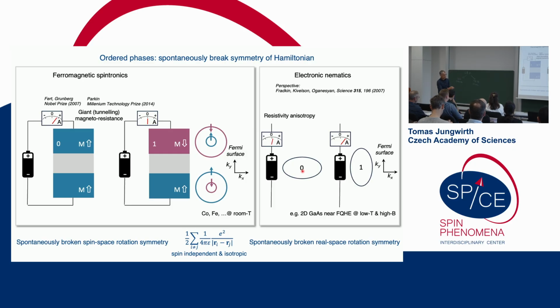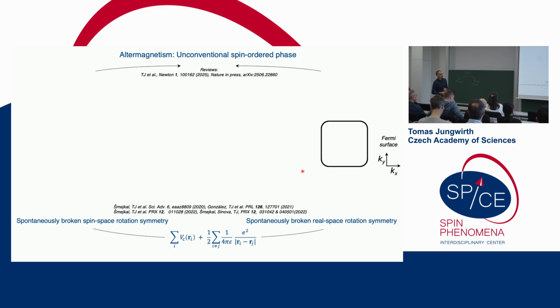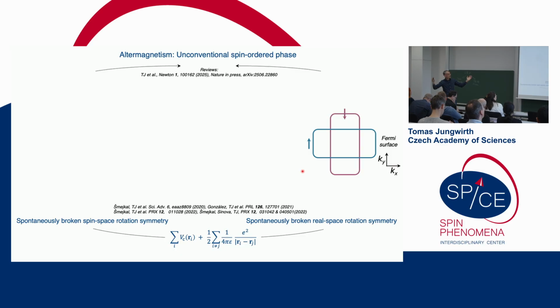Good. So, thanks. So now we're going into our altermagnetic phase, and why we call this phase unconventional is because altermagnetism simultaneously breaks both the spin space rotation symmetry and the real space rotation symmetry. And if we want to see it in the momentum space first, what happens is that the original normal phase, which has the symmetry of the Fermi surface corresponding to the Hamiltonian, now in the altermagnetically ordered phase, we have this anisotropic deformation in each spin channel individually.